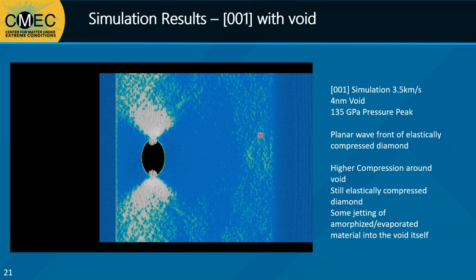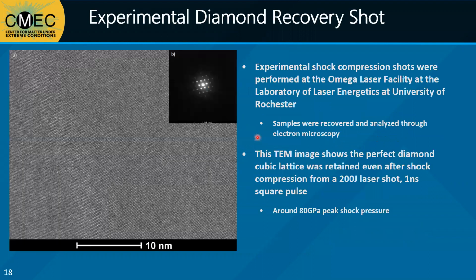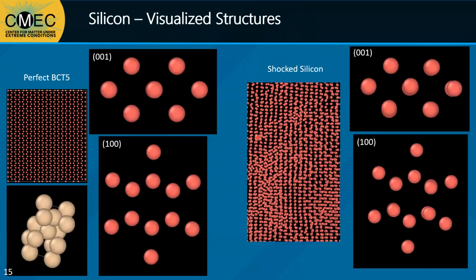Sylvia, please go ahead. Hi, Silvia Pandolfi. Very nice talk. I had a couple of questions out of curiosity. The phase that you identify for silicon, for the high pressure phase, has this been seen experimentally or not? Yes, it has been seen experimentally. Nanoindentation experiments in particular have observed the BCT5 phase of silicon. It is a known metastable phase of silicon.